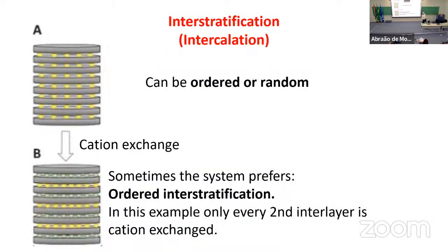Another concept that is going to be important is called interstratification. It turns out, in what I'm going to show you, that the clays really like to have ordered interstratification. If you do this cation exchange, and then you dry the system afterwards, the clay really likes to have different cations in every second layer. And that is important for the applications I'm going to mention.